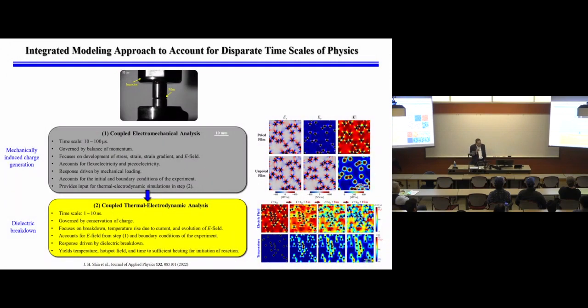So here is what actually happens. When you apply the mechanical loading, at some point you have the chemistry there, and you actually have two processes. The first is that when you apply mechanical loading, the stress generates an E field through piezoelectricity and flexoelectricity, so you have E field generation, charge generation in the material. And this is actually for both. Piezoelectricity has to be poled. For PVDF, you apply a voltage, you induce a polarization. That's how you can have piezoelectricity. So we have two versions: poled materials and unpoled materials. Poled materials have both piezoelectricity and flexoelectricity.